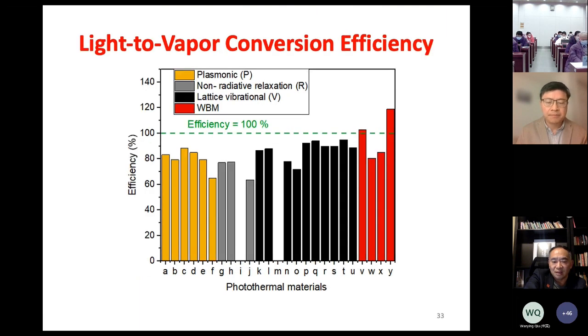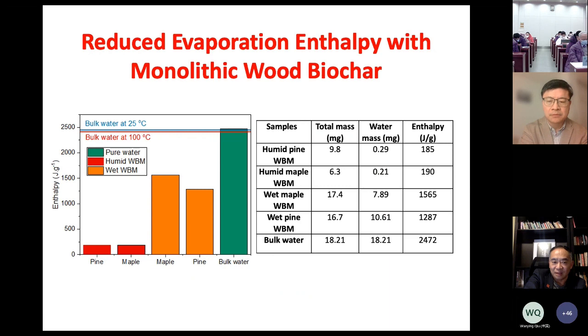Okay. Here we also can calculate the light to vapor conversion efficiency. It's interesting that some of the efficiency is higher than 100%, which was a puzzle for us. But in the end, we found that the fundamental reason for that is this result. What we found is that the monolithic biochar can reduce evaporation enthalpy, meaning that the water confined in the biochar needs less heat input to be evaporated.